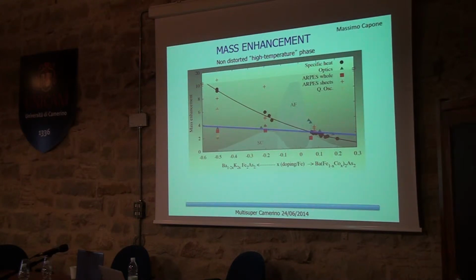These of course are measurements that do not care about the different orbitals and different bands. You just measure one specific heat, one Drude weight, one optical conductivity. Now I show you also some results from angle-resolved photoemission and quantum oscillations. These are all measurements that instead are sensitive to the different pockets and different pieces of our Fermi surface. And you see that these spread. And essentially they spread more in the regions where there is a spread between the 2 original estimates. So essentially what I'm telling you is that when you go in this direction, the effective mass increases, but it does so in a very orbital selective way, or at least band selective way.